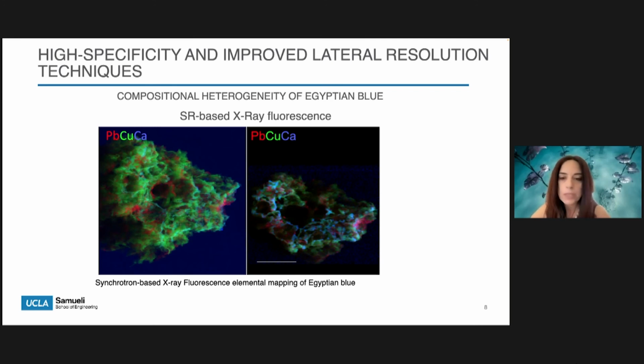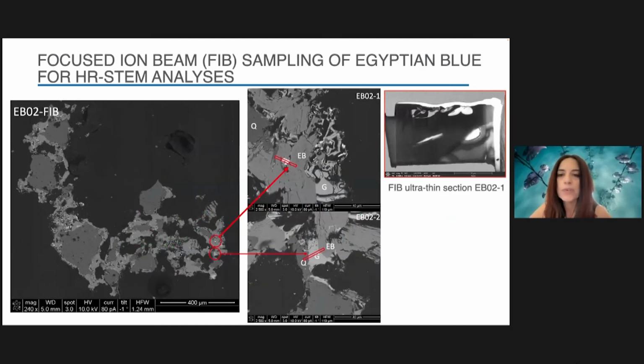To answer these questions, scanning transmission electron microscopy was used. This has helped us take things one step further, as it enabled us to visualize and identify both crystalline and amorphous phases at the nanoscale and complement results from the SEM and synchrotron analysis. So to analyze samples with the STEM, we first used focused ion beam on a polished cross-section of Egyptian blue to slice an ultra-thin section across areas of interest.